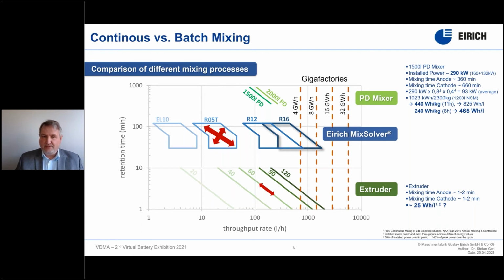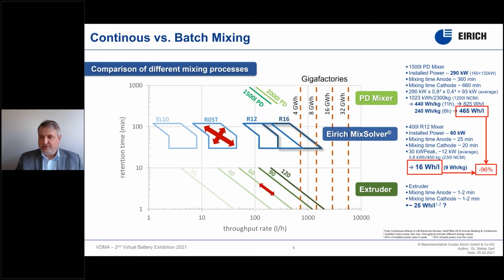But if you really compare the installed energy, the motor power and the throughput rate, this value should be significantly higher. On the other hand, by experience in production plants, we know that with a 400 liter R12 mixer and the 230 liter NCM cathode material, we have an installed power of only 60 kilowatt. We have a mixing time of about 20 minutes for the cathode material. We need 3.8 kilowatt hour per 450 kilogram, and by this we are ending up with a value of only 16 watt hour per liter. And if we compare this value with a traditional value from the planetary Dispermix mixer, we see that we can cut down the energy consumption by 96%.